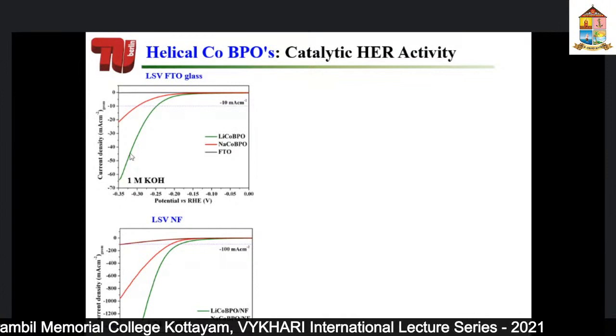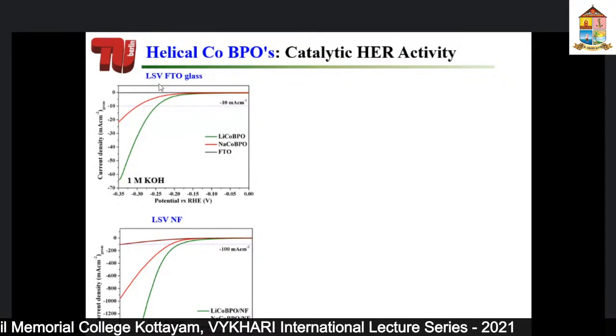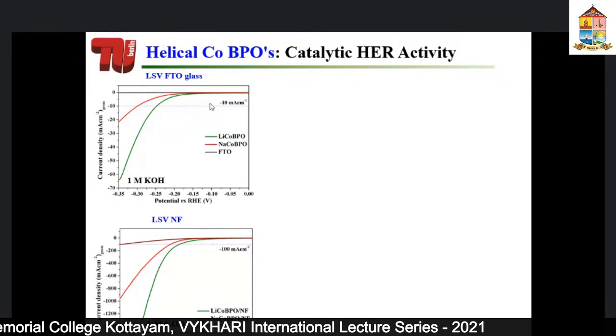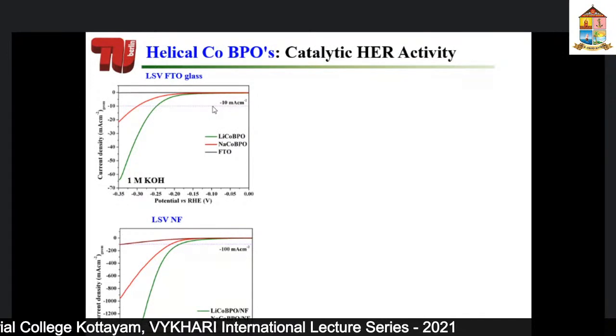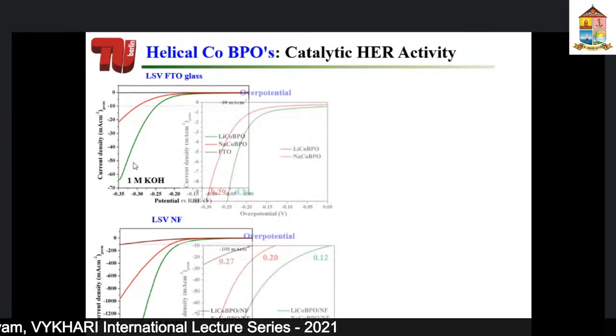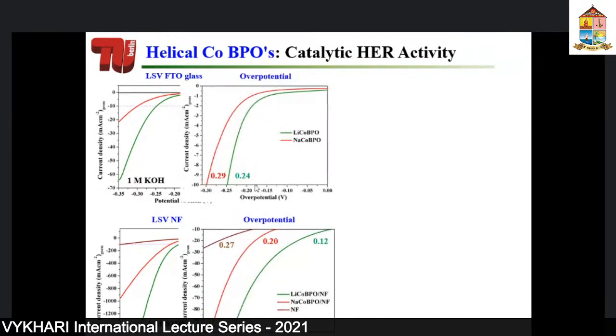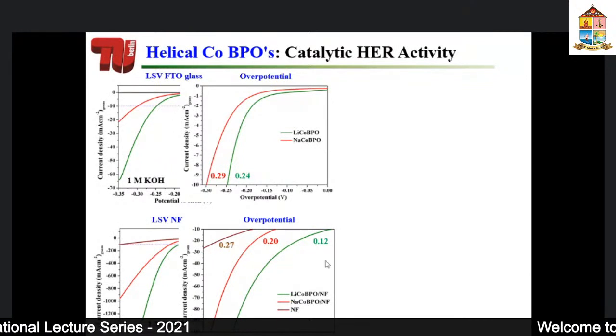So we also checked the LSV, which means linear scanning voltammetry, which is very similar to CV, but you don't cycle, which we did also in alkaline solution. And you see that we have a very nice hydrogen evolution reaction. These curves indicate that we have hydrogen evolution. And we can also determine the overpotential. We have almost 240 millivolt of overpotential, and here it's almost 100. Just remember that the thermodynamic potential for hydrogen evolution is 0. So we need almost 100 extra potential here and almost 240 extra potential here to drive the reaction.